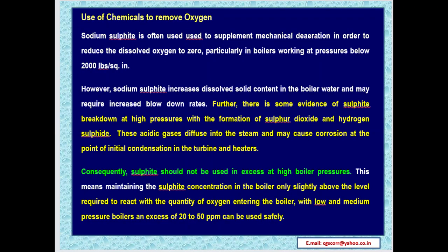Use of chemicals to remove oxygen. Sodium sulphite is often used to supplement mechanical deaeration in order to reduce the dissolved oxygen to zero, particularly in boilers working at pressures below 2000 pounds per square inch. However, sodium sulphite increases dissolved solid content in the boiler water and may require increased blowdown rates. Further, there is some evidence of sulphite breakdown at high pressures with the formation of sulfur dioxide and hydrogen sulphide. These acidic gases diffuse into the steam and may cause corrosion at the point of initial condensation in the turbine and heaters.